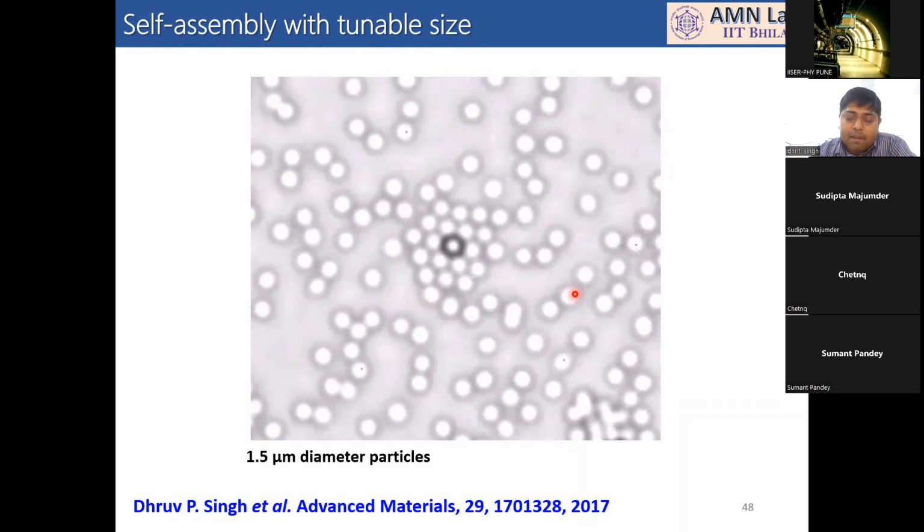Okay, and the other question is, do we also have a limitation on the size of the TiO2 layer deposited in order to have these modes? That is simply governed by the semiconductor property of this material. If it is too thin, then you will generate a very small number of electrons and holes, so your activity will be small and your swimming speed will be lower. On the higher side, there is no problem. You can go 200 nanometer, 300 nanometer, whatever you want, but then you will get saturation.